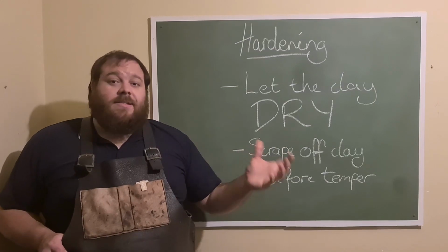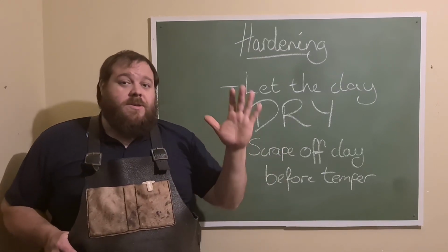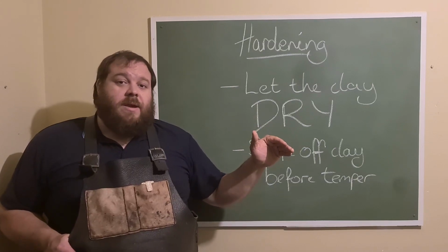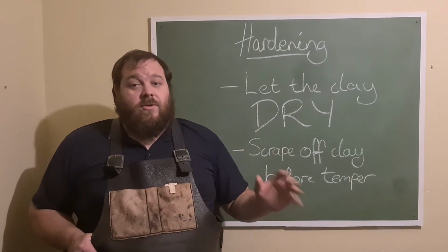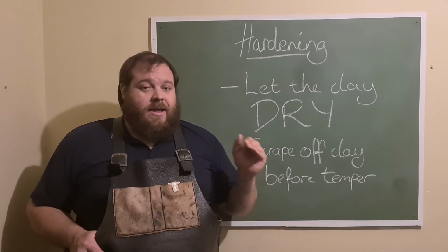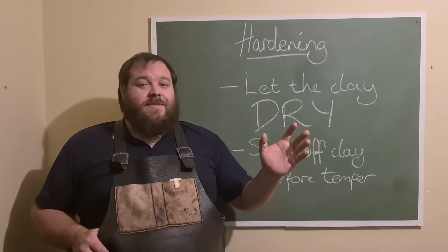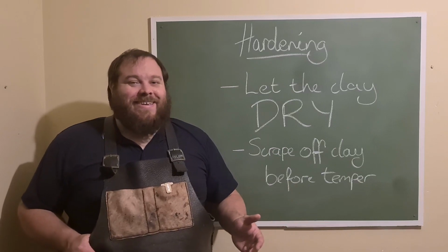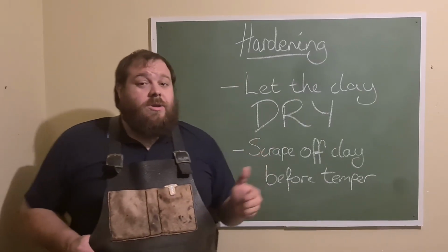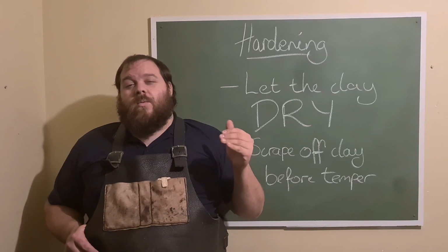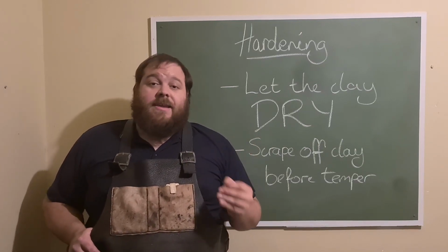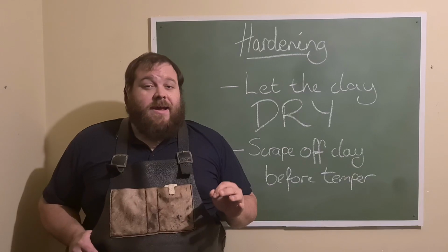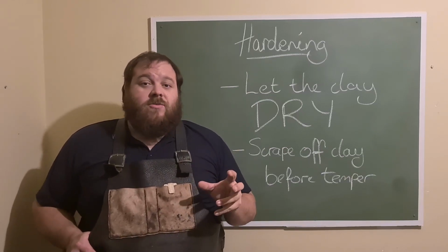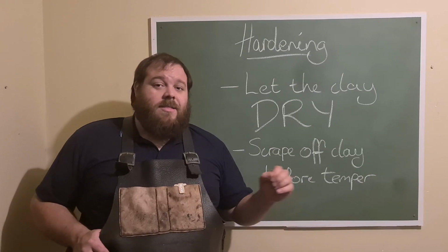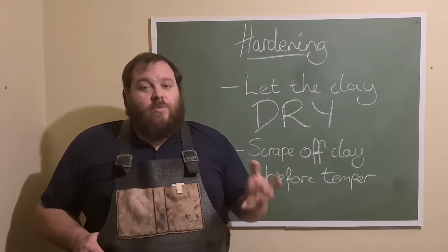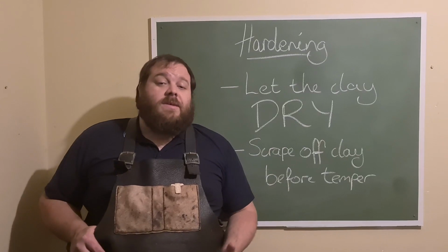And you do this exactly as you would any other time. You get it up to temperature, and then you go into your quench media. You leave it in the quench media. If you're using clay, you put it in and you leave it there until the bubbles stop, just like you're drowning someone, as my friend Alex would say. But what should happen is that it should harden without popping the clay off. If the clay does pop off, that is not necessarily a bad sign. The clay can pop off during the heat treatment, or hopefully it pops off after the Hamon has set in. If it doesn't, you will know once you get to the grinding stage, because you won't see the Hamon anymore.